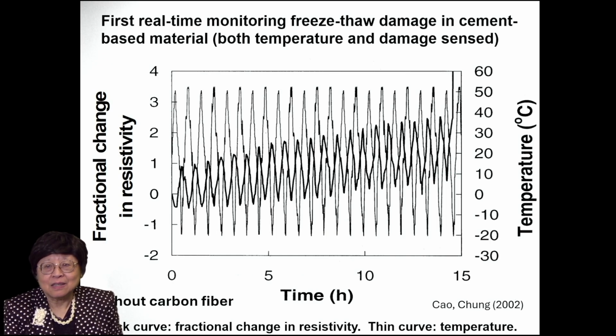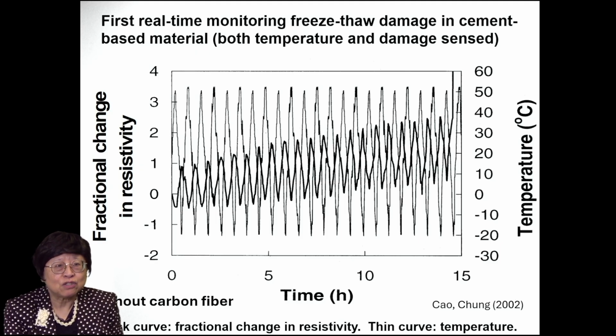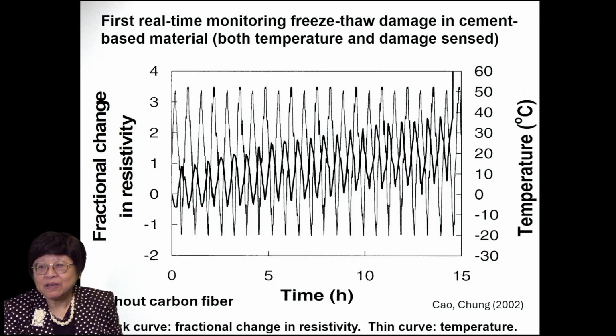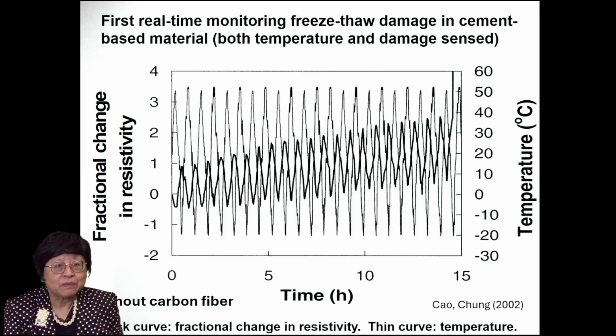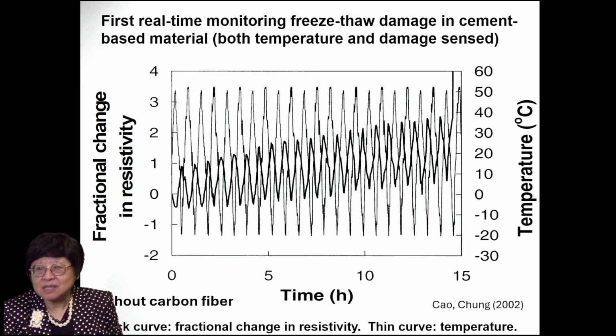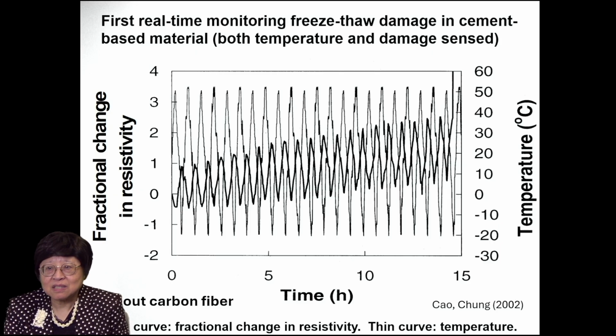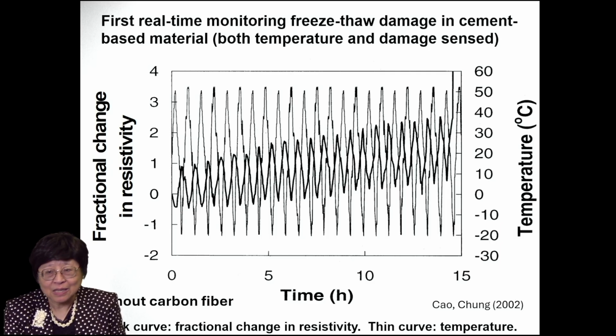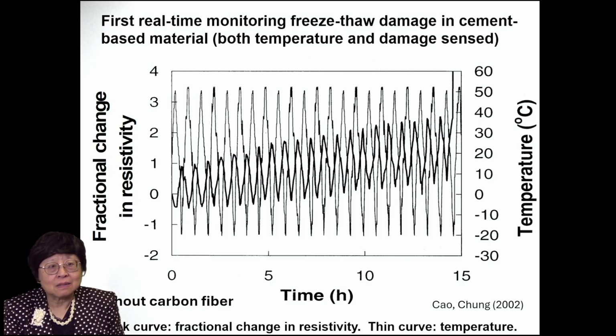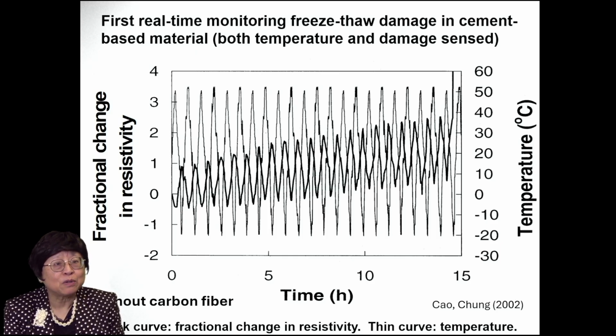However, I used resistance measurement to monitor the freeze-thaw degradation in real time. And shown here in thin line is the temperature, and the full line is the resistance. Whenever the temperature increases, the resistance goes down, and that is simply because there are interfaces in the material, and an increase in temperature would increase the thermal energy, and so makes the jumping of the electrons across the interfaces easier. And so the cement-based material is a thermistor, a temperature measuring device.